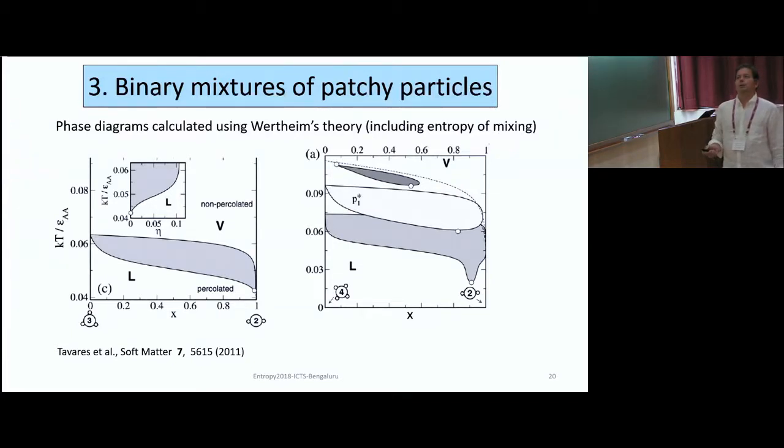And you can see that at this pressure, you can have liquids with fewer and fewer three-patch particles, and more and more two-patch particles, so long chains and some branching, until you go almost to, this is the density-temperature projection of this phase diagram, almost to density 0. So if you have mixtures of 2 and 3, this suggests that you can still have this phenomenon of empty liquid in this system.